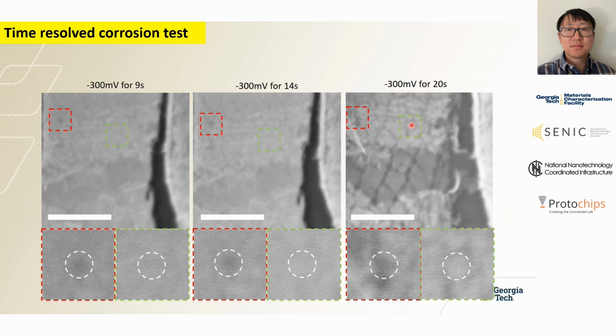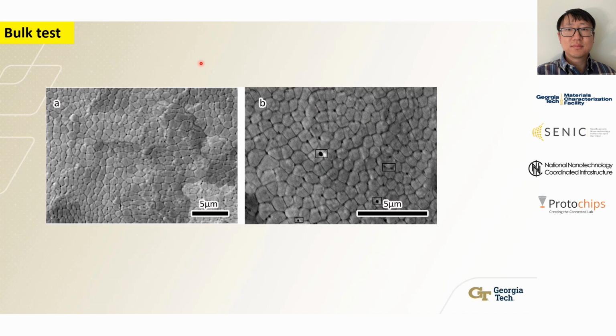It's not corroded. So we also apply cyclic voltage on the bulk sample, by applying the voltage from the open circuit voltage to 1 volt and coming back. And this is the SEM image for the bulk test after a corrosion test. We can see the cell boundary gets corroded, and from the zoomed-in image, we can see the oxides become larger at the cell boundary. But if we look at the oxide inside the cell, it doesn't change size at all. It might just dissolve in the solution, but didn't change size. That means the oxide at the cell boundary has severe corrosion, but inside the cell, it just dissolves and nothing more happens.